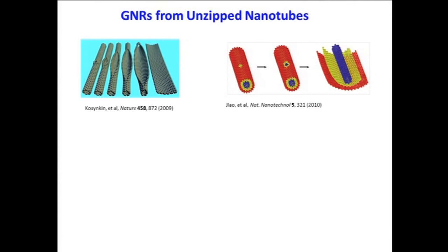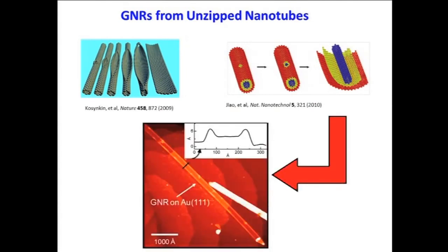And so what I want to show you now is some results that we got looking at these nanoribbons. And here's the recipe for how to make them in this paper. So Hongjie Dai gave us some of these nanoribbons, and we spin coated them onto clean gold crystals, and we looked at them with STM, and this is what we saw. This is a room temperature STM image of a single nanoribbon on gold, and it's a beautiful nanoribbon. Believe me, we've looked at a lot of unbeautiful ones. But using this technique, the nanoribbons are almost always really nice. So you can see that it has very nice straight edges.